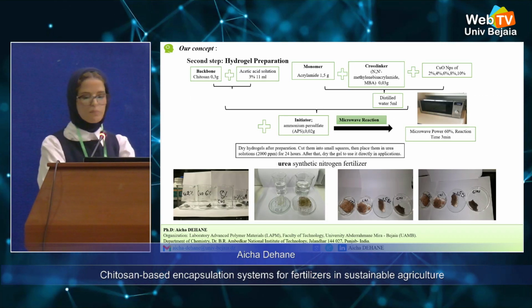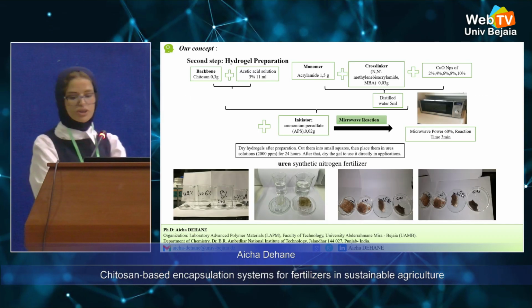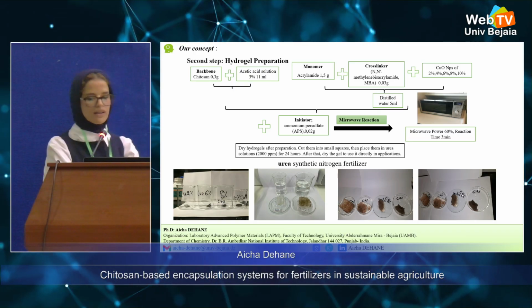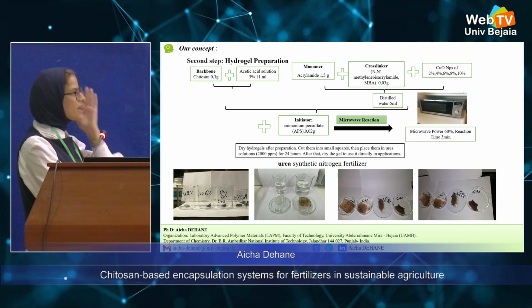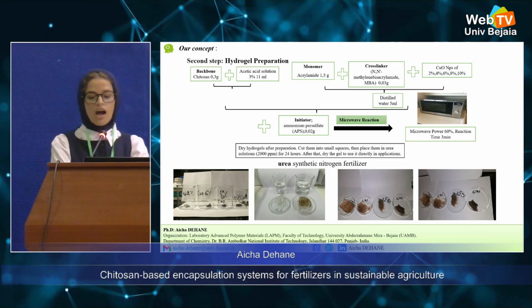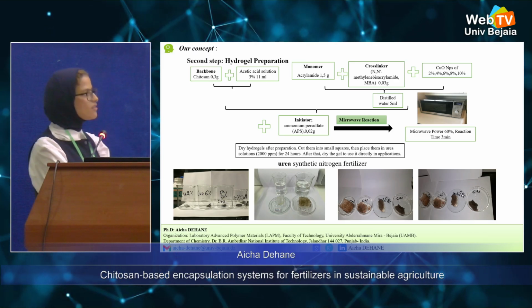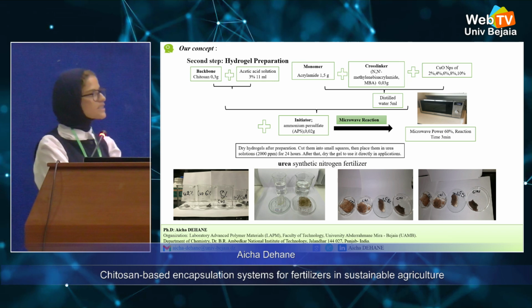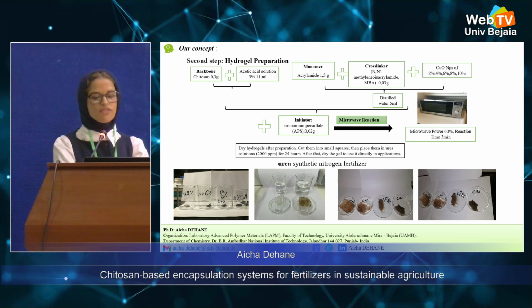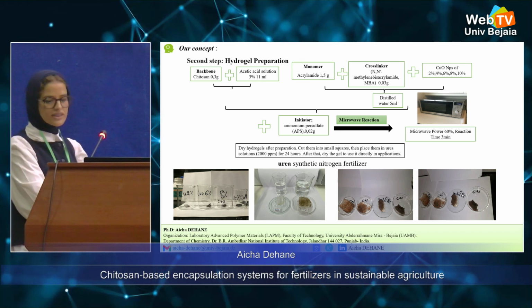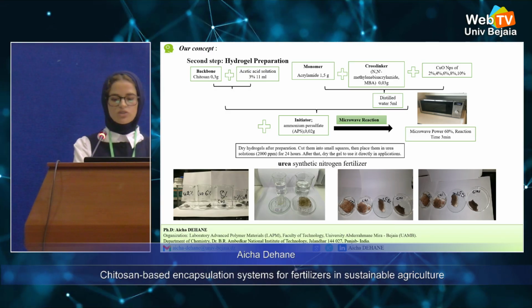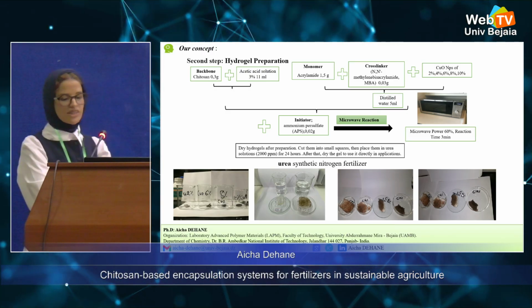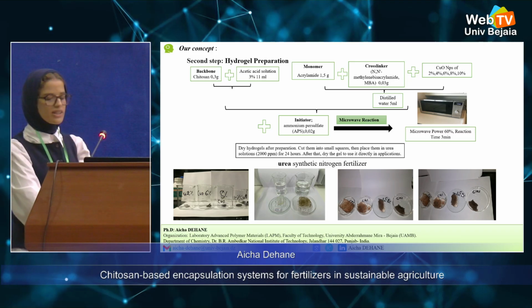After optimizing the matrix with the backbone polymer, acrylamide grafted onto chitosan, we incorporate the nanoparticles into the hydrogel matrix. The obtained hydrogel nanoparticles were soaked in a solution to study their fertilizer encapsulation and controlled release.